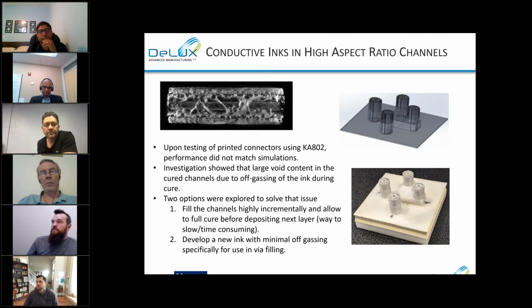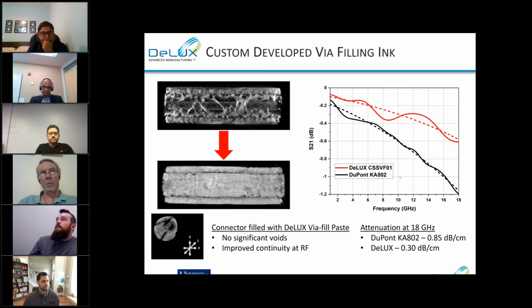We came up with two solutions. One was to vastly slow down our printing process and do very incremental small layers with a full cure of every small layer, allowing it to drive off the gases as we go up in height. That takes way too long. So our next step was to try to develop our own ink based off of what we know about the challenges and the problems. And so we developed a silver conducting ink specifically for high aspect ratio channel fills.